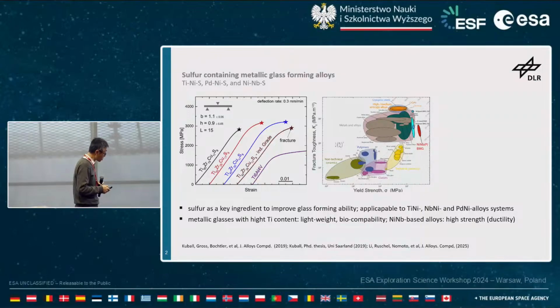And the idea behind this is, on the one hand, metallic glasses, for those of you who are not working with them very often, have quite special properties. On the one hand, the mechanical properties, especially the strengths, are quite good. On the other hand, some or many of them are brittle. But with sulfur, they achieve metallic glasses which can work with a high titanium content, meaning that they are lightweight and also have biocompatibility. And on the other hand, for nickel-niobium-based alloys, where I will show most of the results, they are already quite good glass formers. With sulfur, and recently also with phosphorus alloys, they have both high strength and ductility.